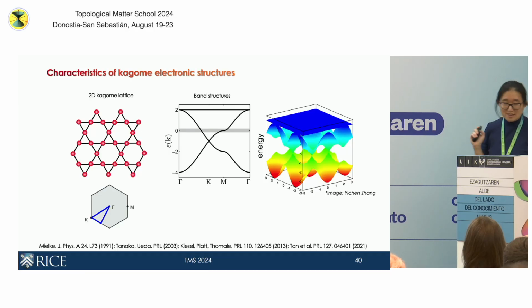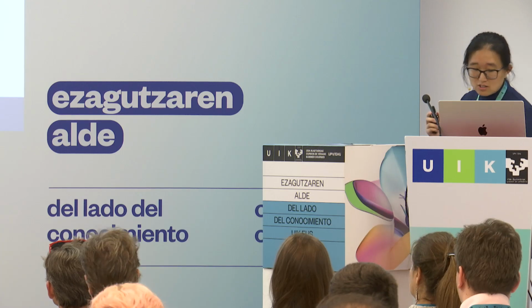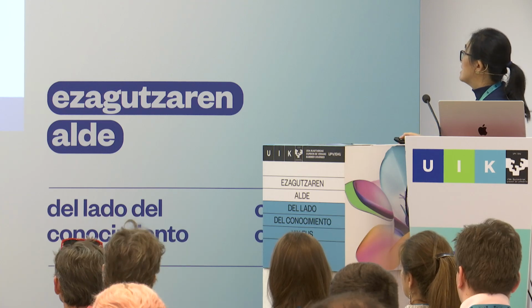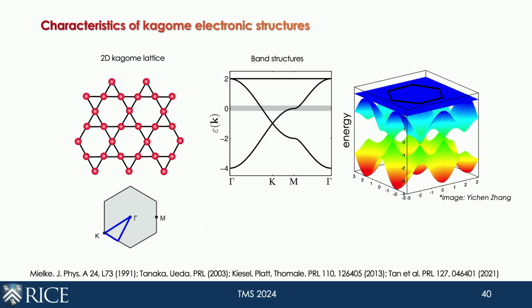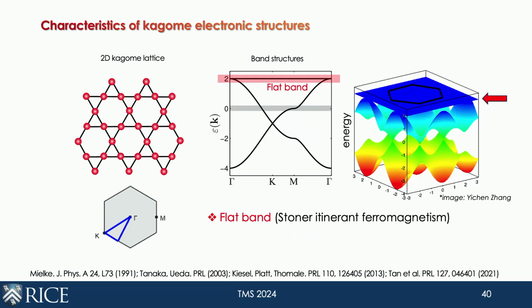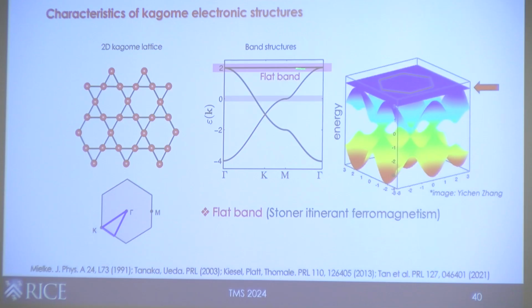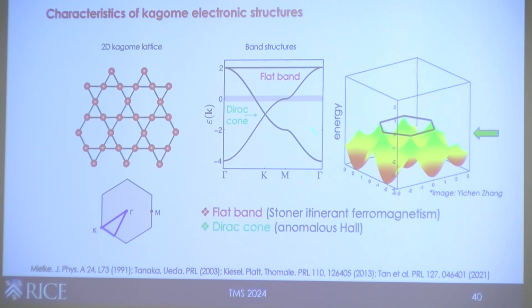I'm going to go really quick on the Kagome since this is already introduced, but just to remind you of the 3 key signatures in the electronic structure that arise out of this lattice. The most important one is the flat band, which, if you tune your chemical potential to be in the flat band, then at least one of the ground states is this Stoner itinerant ferromagnetic order that arises because of the large density of states. And then we also have the Dirac cone, and if you incorporate spin-orbit coupling, that becomes gapped, gains Berry curvature, and then you can have anomalous Hall. Stephen's also giving you examples of this.